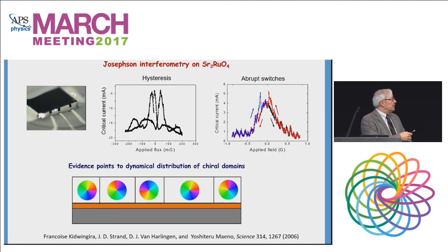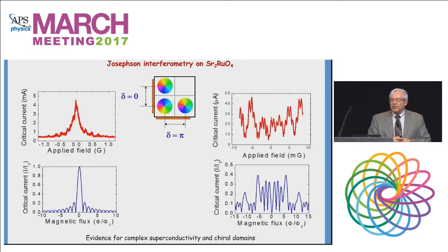And so you could design an experiment to test this directly, such as shown here, which is sort of a modification of the corner SQUID. If you have domains of this type, then, as often happens in the cuprates, in one direction they align and you get very large critical currents in a Fraunhofer-like pattern. If you look in the other direction, they're out of phase, and you get a very suppressed critical current, about 100 times smaller. And you can see that it has this modulation form reminiscent of a grain boundary junction, again showing this chirality and the presence of domains.